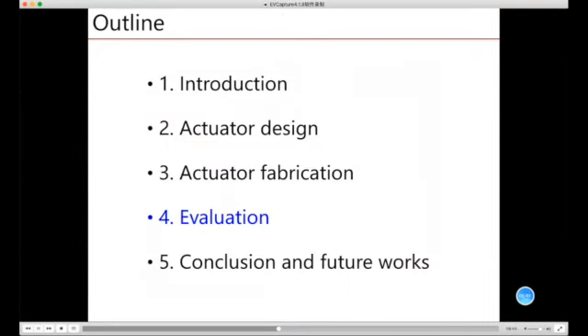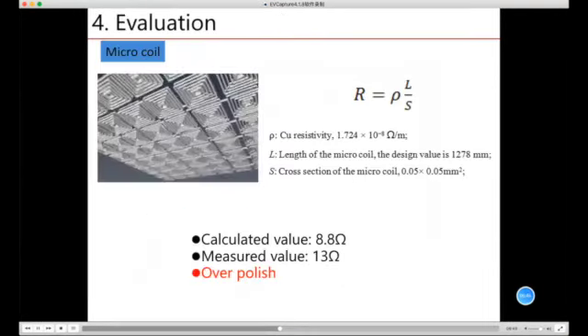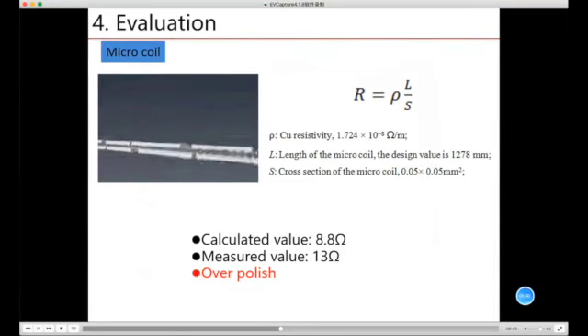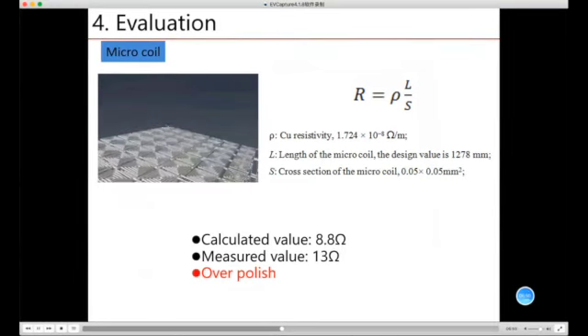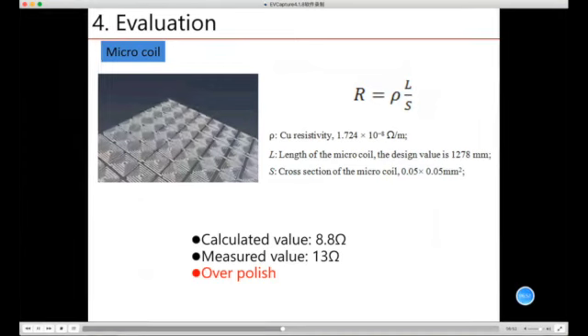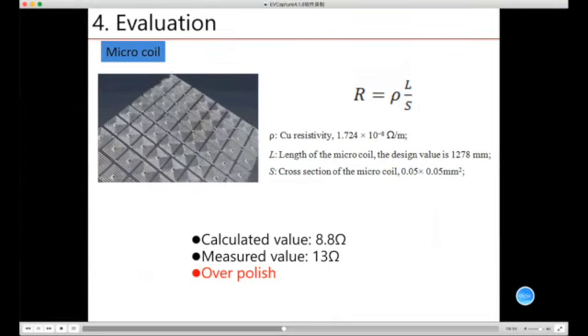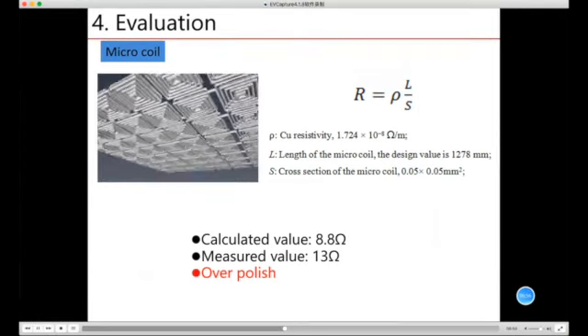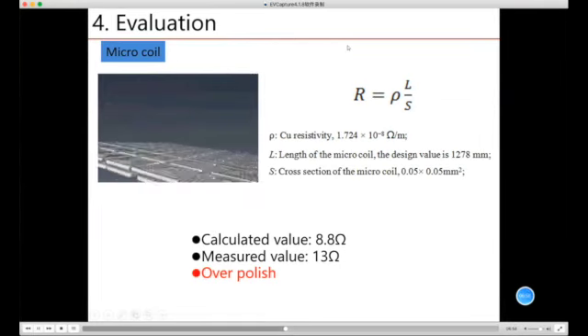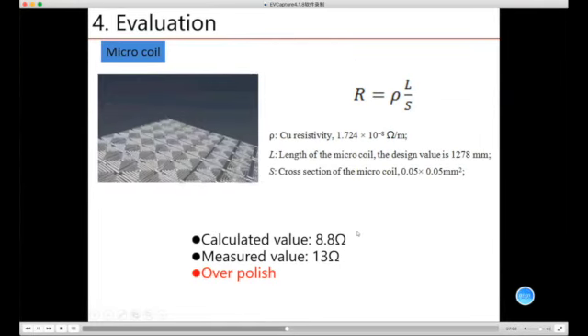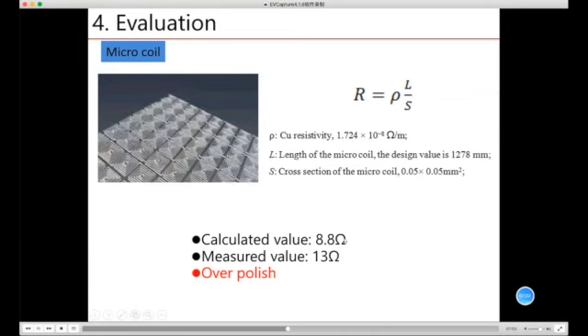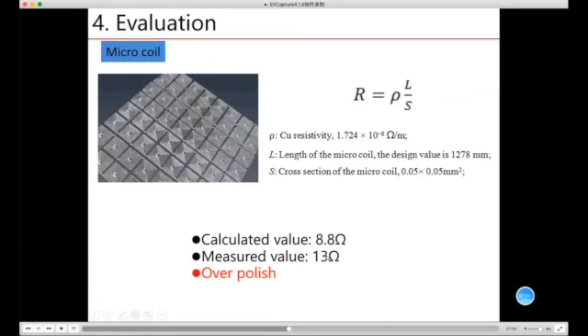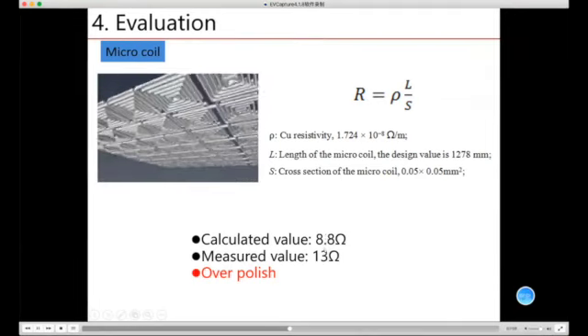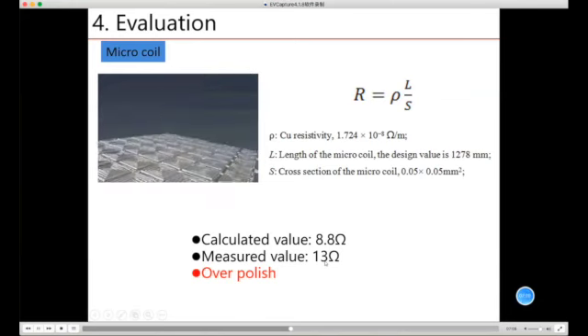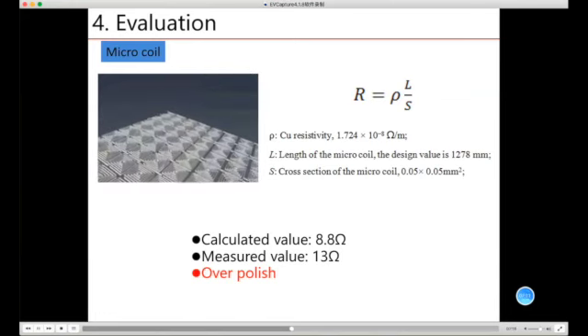Then comes to the evaluation. First, for the microcoil, in order to test its connectivity, we measured the resistance and calculated the resistance. For the calculation, we use this equation. The calculated value is 8.8 ohm, and the measured value is 13 ohm. The difference between the calculated value and the measured value is maybe caused by the over-polish during the microcoil fabrication.